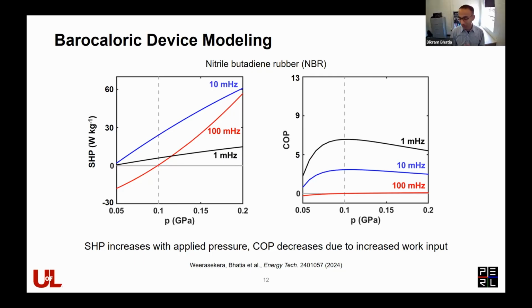Yes, that's another very good question. So there is a lot of work that the material scientists are doing on hysteresis. This hysteresis is particularly a problem for the materials that have an order-disorder phase transition, which remember are the materials that we're most interested in. But that was another reason why we did not choose, at least as a first step, to go into using these materials with solid phase transitions, because the hysteresis is substantial, like on the order of about 10 Kelvin when you have your delta T span of 30 Kelvin or so.